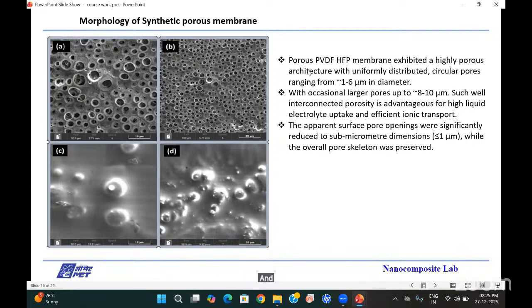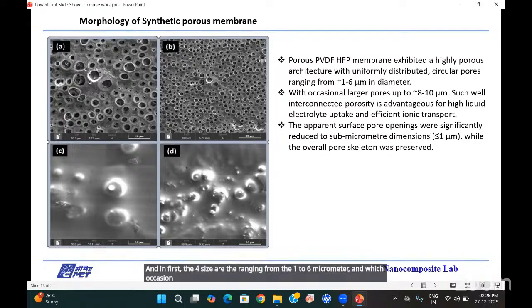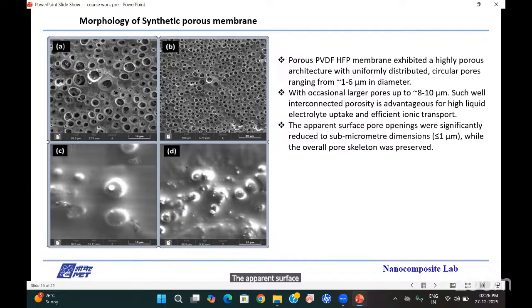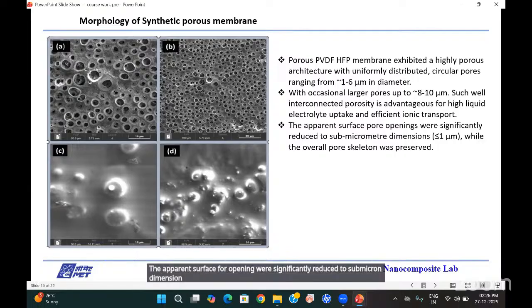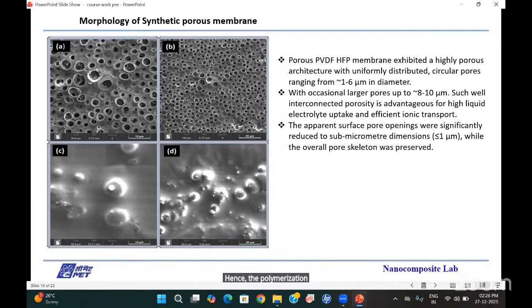At first, the pore size ranges from 1 to 6 micrometers, with occasionally larger pore sizes of up to 8 to 10 micrometers. The apparent surface pore openings were significantly reduced to submicron dimension after polymerization. Hence, the polymerization is also confirmed by the SEM images after polymerization.